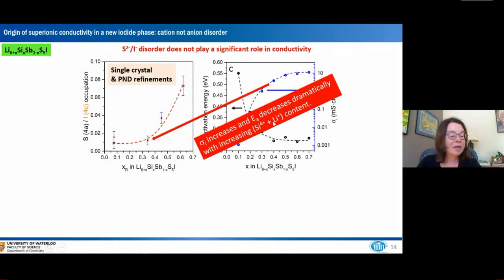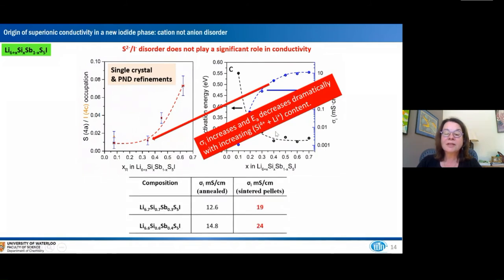And this is the main point: we can see that anion disorder does not play any role whatsoever. It really is the lithium content that is affecting things. We're getting conductivities upwards of easily 20 millisiemens per centimeter, either for annealed, 15 to 20 for annealed versus sintered pellets. So these are superionic conductors.